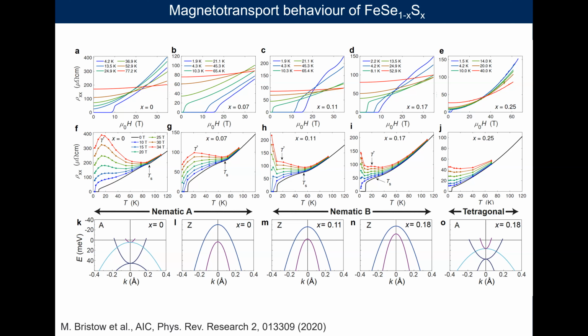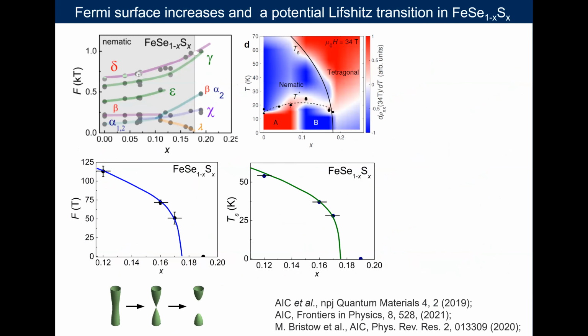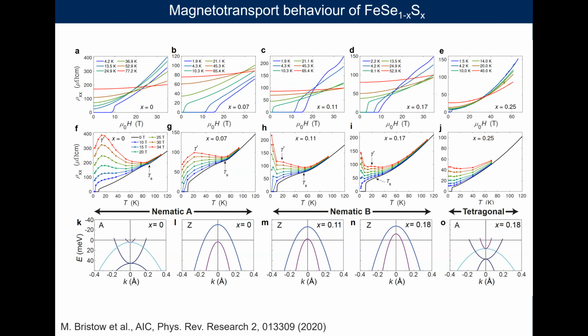So you see, as we go in the phase diagram, the transport and the magnetotransport really change quite sensitively with where we are in the phase diagram. And if we put all these results together, what we observe is that in general, the Fermi surface does increase with chemical pressure, but there is that particular low frequency, which we call lambda here, which seems to appear at the same place where the slope of resistivity changes. So here we plot, you see this is a different slope than this slope.